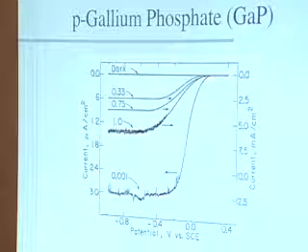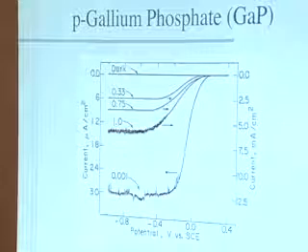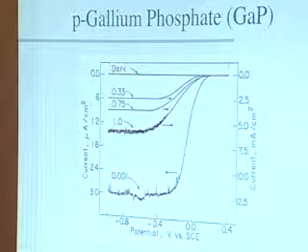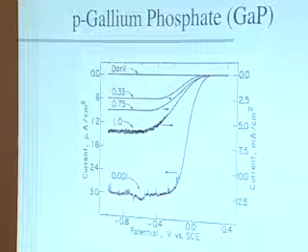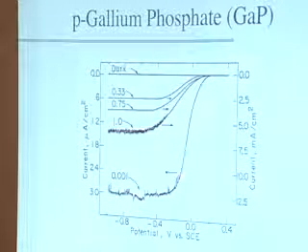And then as you turn on the light at higher and higher intensities, you see generation of hydrogen, and again, about 300 millivolts of band bending is needed for efficient electron-hole separation. What you may not be noticing here, but I'm sure Bruce has, is the currents are much smaller than in the other scheme. This microamps per square centimeter only refers to this line right here, which is at very low intensity.